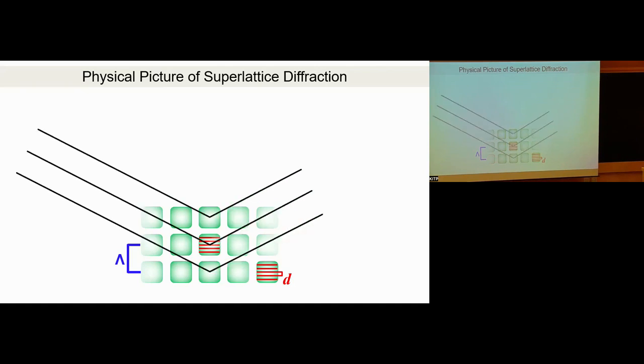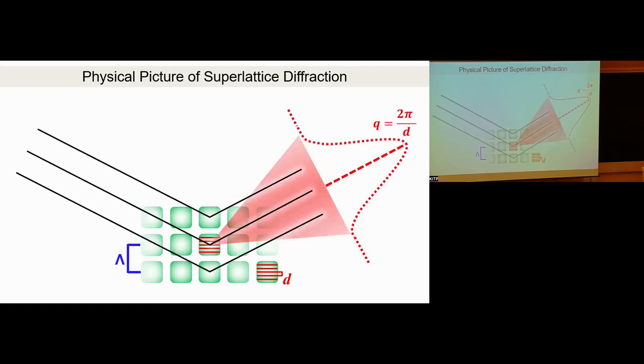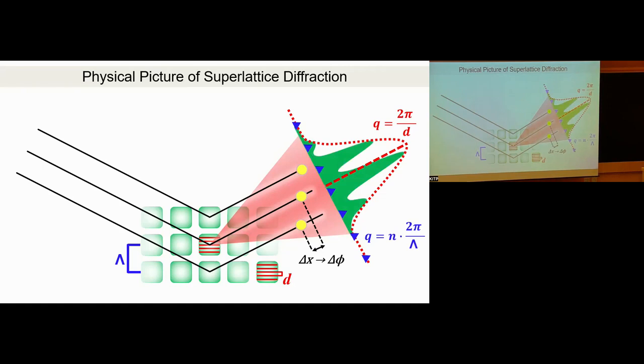So when X-rays fall on the sample, first each nanocrystal contributes a Bragg peak at the position of the lattice constant, with broadening because of the finite crystal effect. And then there is an additional phase shift due to the superlattice periodicity, which shows up as this diffraction grating, if you will. Then the two effects combine and give this superstructure of the first Bragg peak.